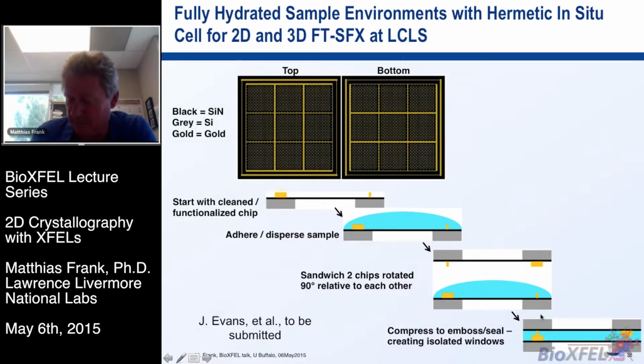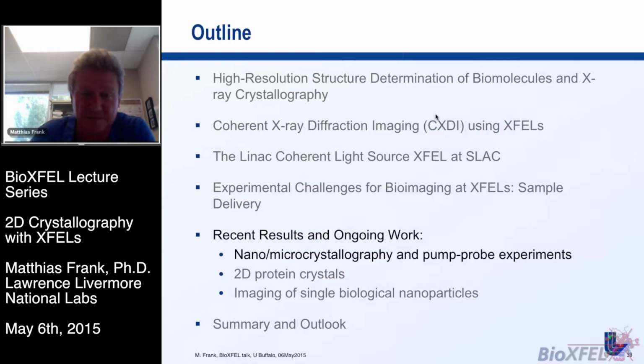So instead of having a 100 by 100 or 200 by 200 micrometer large single membrane, you basically have a little compartment that is that size, a square compartment or elongated compartment where the water is enclosed. These gold spacers serve as spacers, so you enclose a small amount of water. There's not a large amount of liquid in there, and they also seal individual cells from each other. So you can have a wafer that has of order 1,000 of these cells, and you can shoot out these membranes as you do with the other fixed target approach, except that now your sample is in water.